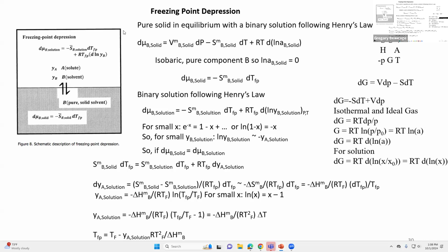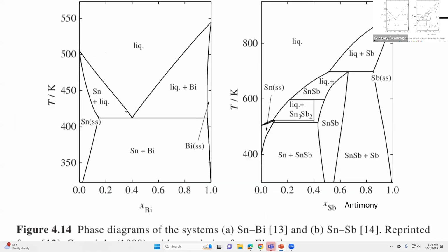You're going to add something, and is the melting point going to rise or drop when you add the other stuff? The answer is it always drops, because this equation says it's negative. So it has to drop, and it's at dilute conditions, the Henryan regime, not the Raoult. So the dilute regime is always going to be linear at the beginning. The beginning of this point has to be linear. So it is there. That's kind of how it should be. And it's linear over here too when you dilute the other way.